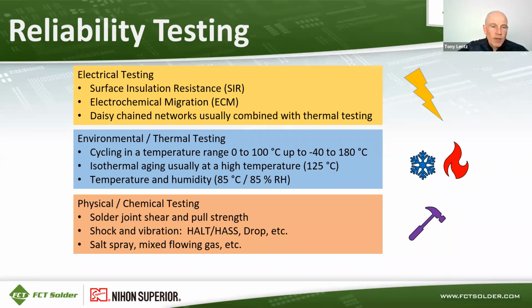And then finally, of course, we can perform physical or chemical testing on the PCBAs. Solder joint shear and pull strength is commonly done to measure the strength of the solder joints or the assemblies. Shock and vibration testing is also used in some cases, which could be half-sine pulse testing, drop shock testing, and the like. And then if you require chemical testing, for example, if circuit boards are going to be mounted in, say, electronics that are used in ocean environments, you might want to subject them to salt spray testing in order to see what happens with salt corrosion on the electronics.